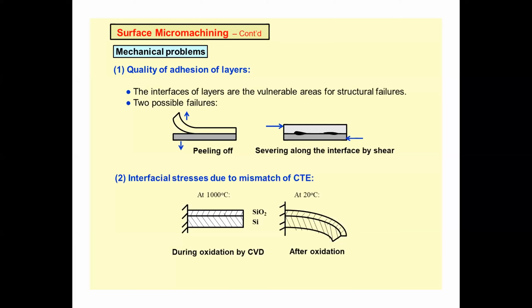The beam can get peeled off, and there can be stiction because some other material or an air gap can get trapped inside, and that can create shear stress. And then there are interfacial stresses due to mismatch of the coefficient of thermal expansion, that is CTE. Say the deposition may be happening at 1000 degrees centigrade, and the coefficients of thermal expansion of silicon and silicon dioxide are different, which means that when the temperature is reduced from 1000 to 20 degrees centigrade, the contraction in silicon will not be the same as the contraction in silicon dioxide. This means there will be bending due to this contraction after oxidation at room temperature. So this also may create some problems in surface micromachined devices.